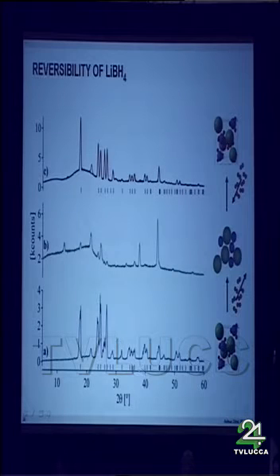And here are the corresponding X-ray diffraction patterns for the initial compound, for the desorbed compound, and here for the reabsorbed hydride. And you can see the reabsorbed hydride structurally looks even better than the initial compound. So this is the other rumor, that borohydrides are intrinsically not reversible. That is not true. Borohydrides may be reversible, at least partially, just like the alanates.